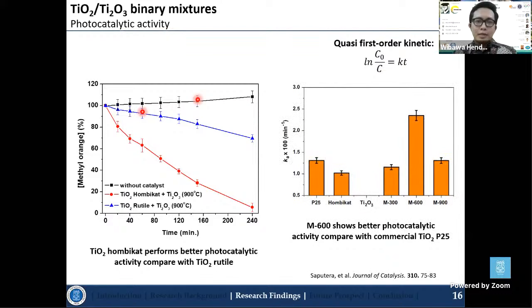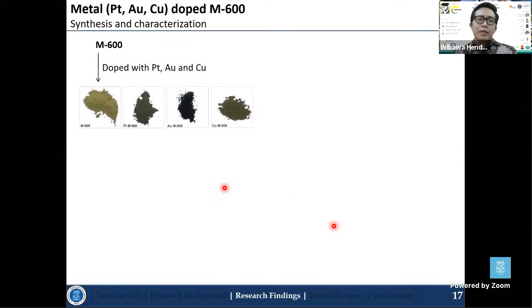And using this formula, in order to determine the rate constants, it seems that the mixtures which calcine at 600 degrees C or M600 exhibit the best photocatalytic performance. And when compared with the commercialized one, which is the Degussa P25, and also the parent titanium dioxide anatase, the M600 show better photocatalytic activity by around 2 times or 2-folds. So in order to enhance the photocatalytic efficiency, I dope the M600 with the several metals such as platinum, gold, and copper.